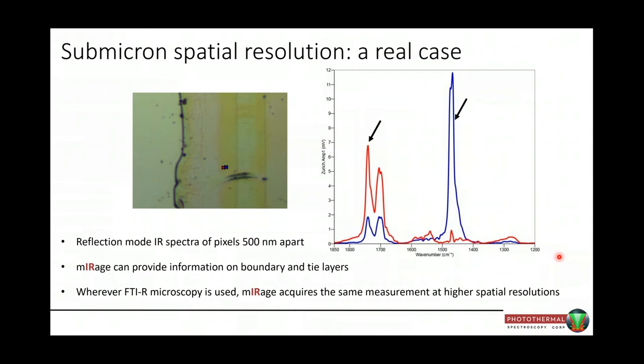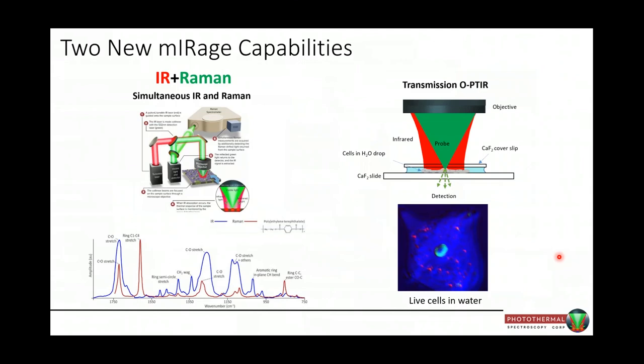There are two new capabilities that have just come around. One of them we're going to talk about today is the combination of IR and Raman. And here's an example of a spectrum of polyethylene terephthalate, and it shows the complementary nature of the information that comes from the infrared spectrum recorded in blue and the Raman spectra in red.